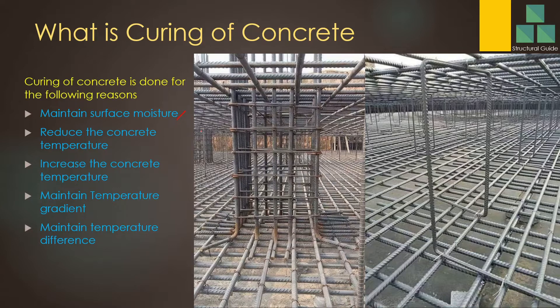Reducing the concrete temperature is the most important thing for thicker concrete. Here you can see very thick concrete. With high grade concrete, the core temperature will increase. As a general norm, we maintain it at about 70 degrees. If it increases beyond that point, there is a chance of forming delayed ettringite. Formation of delayed ettringite could cause cracking of the concrete, as it increases the internal volume and then causes cracking.